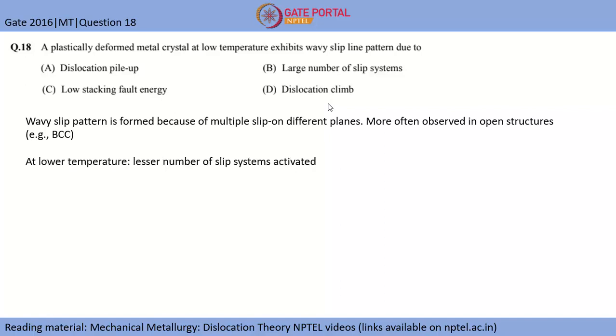And also as it is mentioned, at lower temperatures fewer slip systems are activated, because the movement of dislocations requires higher temperature. If you have read about Schmid factor, if the plane is aligned at 45 degrees to the principal normal direction, then slip will be activated in that slip system. Otherwise other slip systems won't be activated. Hence at lower temperature the tau CRSS required to activate slip is higher. Hence, fewer slip systems are activated at lower temperature.